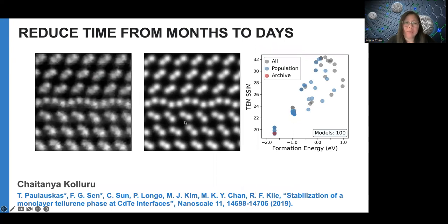So with FANTASTX developed, we took one of the previous examples we worked on. This was a single layer of tellurium sandwiched between cadmium telluride. It just formed by itself. It was really interesting. To find the model that fits this by previous methods, a lot of hand tweaking, staring at it, using intuition, took a few months. And then once FANTASTX was developed, we gave it this image, and after a couple of days on the cluster, it found the correct structure, and not even that many structures were sampled. This was a rather simpler interface, but still, I think the time saving is there.